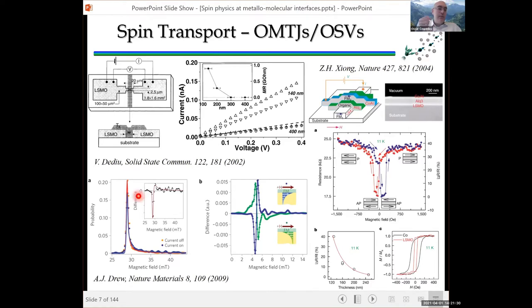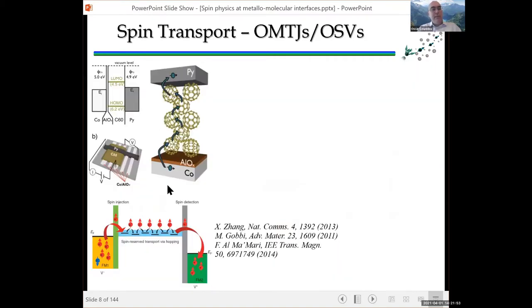So what they do is they inject muons, and they look at how the muons precess in the local magnetic field. I will discuss this a bit more later on. And they could study this way the local magnetic fields induced by the spin current coming into the organic from this spintronic device. People were interested in this, and they wanted to replicate the effects on molecules that didn't have metallic centers and could be grown in ultra high vacuum more easily than phthalocyanines perhaps, which is the case of C60.